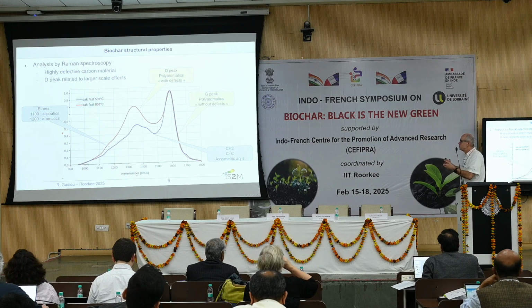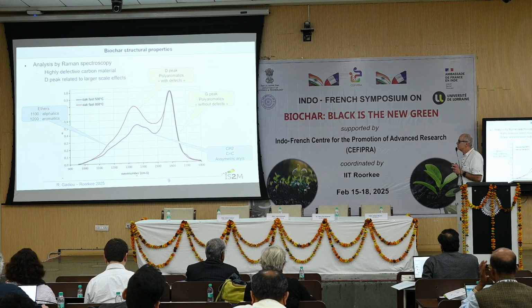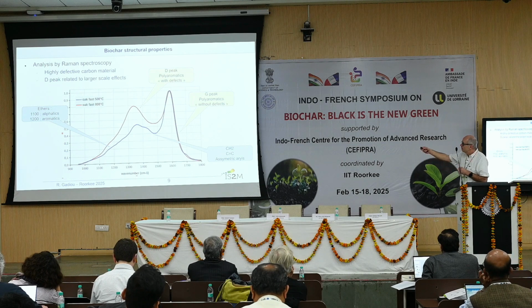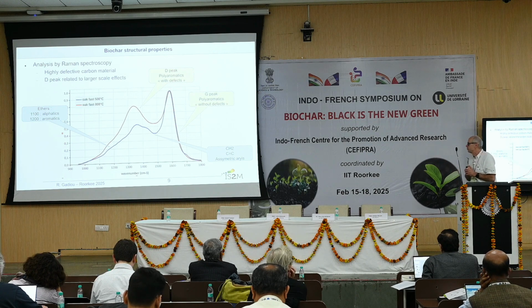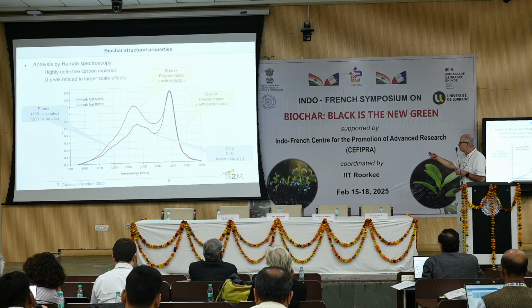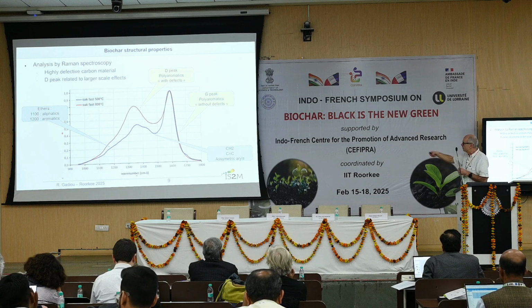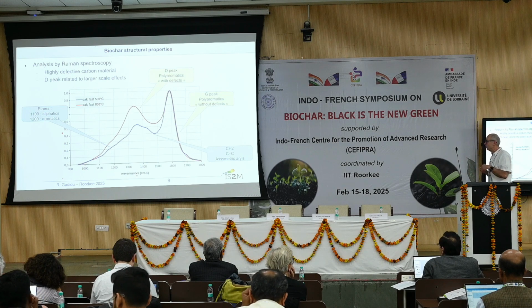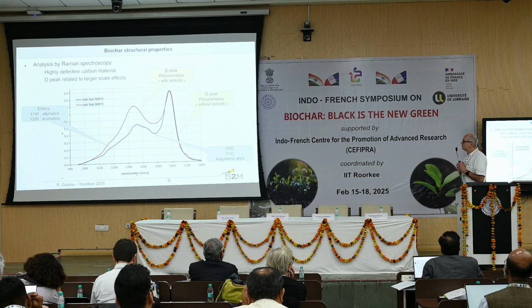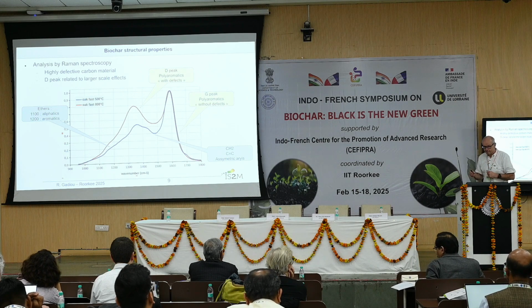Coming to most biochar, which are around 500, 600 Celsius degrees, it's much more complex because we see that we have more satellite peaks, which are related to some kind of bond, showing that there is already some oxygen with the ether bond, or some defect which shows that we have double carbon bond, or CH, methylene, asymmetric array, and so on. So the decomposition of this spectra may be challenging.